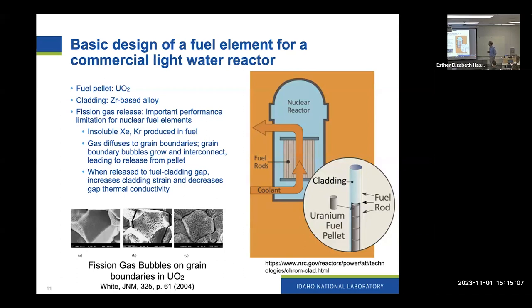One of the main performance considerations of these fuel elements is fission gas release. What that means is that fission occurs, and we produce insoluble gas atoms such as xenon and krypton. Those gas atoms sometimes form small bubbles within the grains, but principally they diffuse to grain boundaries. The bubbles form on the grain boundaries and then grow and interconnect. You can see the progress of that process in a UO2 fuel pellet here.